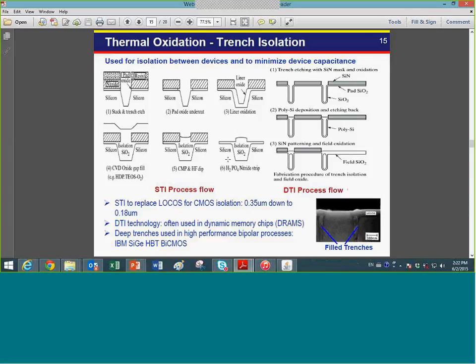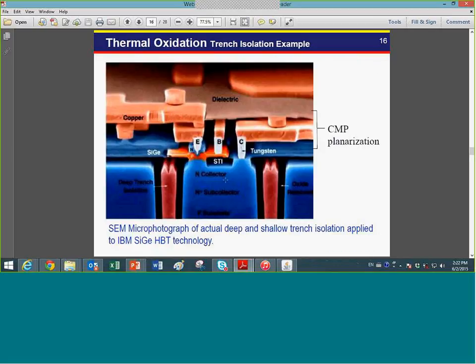So this gives you a quick sketch of STI and DTI. Basically, you need to trench into the silicon, then oxidize and refill with silicon oxide and polish, using the CMP chemical mechanical process. For DTI, instead of filling the trench with an insulator, you fill in polysilicon. This can be as deep as 7 to 8 microns deep. The STI may be 0.3 micron deep.